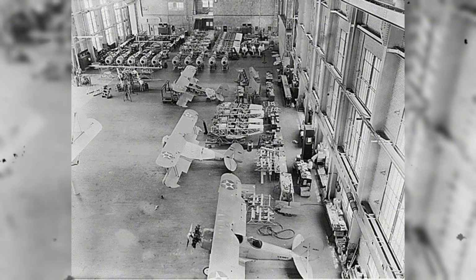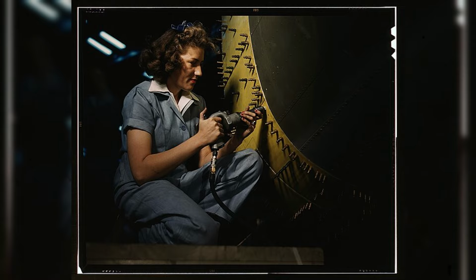By the mid-1930s, aircraft designers had standardized on several nickel-containing alloys. Nickel-chromium molybdenum steels provided exceptional tensile strength and could be heat-treated to precise hardness specifications. Stainless steels containing 18% chromium and 8% nickel resisted corrosion in marine environments, critical for naval aircraft operating from carriers. Engine manufacturers depended even more heavily on nickel.